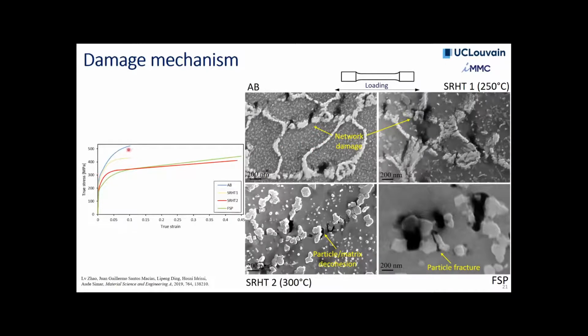The first thing I'd like to mention and identify for you is the modifications of the tensile properties. And as you can see here, in the as-built material and the stress relief, you still maintain this network while you have a low ductility. While here, after stress relief heat treatment at 300 degrees and the friction stir processing conditions, you have a very strong spheroidization of the microstructure. And this spheroidization leads to a difference in the damage mechanism. In this case, we're actually breaking this interconnected network.